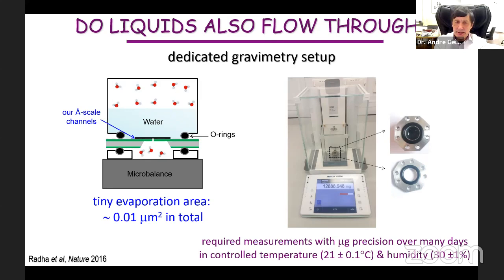Let's see whether liquids go through our channels. In this case, the most obvious is water. We made a few years ago a very dedicated setup. As you see here, we can measure with microgram accuracy evaporation of water from the container. Everything is under control, at controlled temperature, and outside highly controlled humidity. So this is schematic, so what is here? It's our microcontainer on this balance, and when water evaporates, the weight goes down, and this is what we see.